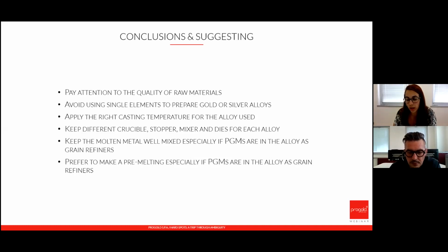Of course, if you start adding variables, like you start having more scraps, or you're not cleaning them properly, or if you're using a low quality of gold, it's going to happen whether you have an open machine, a closed machine, or a continuous casting machine, because it depends on other things. Of course, if you have an open machine, you may get another series of issues because you're not protecting the melt, and you end up having oxide inclusions instead of hard spot. And those are also difficult to remove. It's better to avoid them. If you can, please try to protect the melt, because you're going to get better results if you do that.